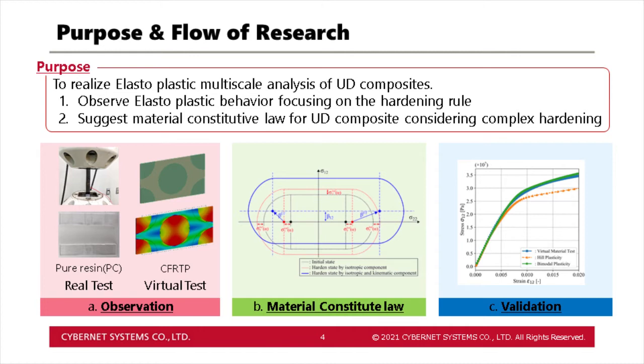The anisotropic material behavior of CFRTP is observed by virtual material testing. In order to perform this analysis, the material properties of the resin and fiber are required individually. Fiber's properties are taken from previous studies. For the resin, the material properties were prepared by realistic cyclic test. Using the uniaxial model created in such a way, virtual material tests with various stress conditions were carried out. From the obtained stress-strain curve, the shape and movement of the yield surface will be observed.